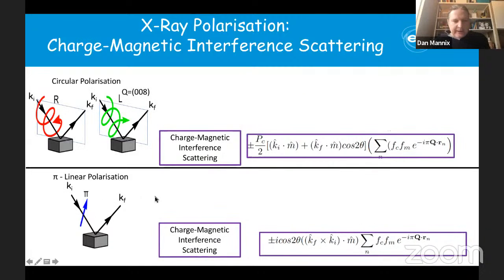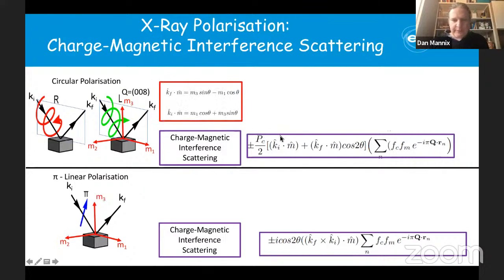So let's look again in a little bit more detail at these interference terms. I'm comparing them here. If I look again at these prefactors, depending on the magnetization measurements, you can see that the kf·m and the ki·m refer to terms inside the scattering plane. So you are sensitive to magnetization in the scattering plane that you are measuring your diffraction in. If you look at the other one, the pi light, you are dependent on magnetization out of the scattering plane. It's the cross product. This cross product gives you magnetization this way. So they give you the same information in the interference term, but they are sensitive to different moment directions of the magnetization. And that's a nice part of this work, that we can actually get different contrasts to different domains just by changing the polarization.